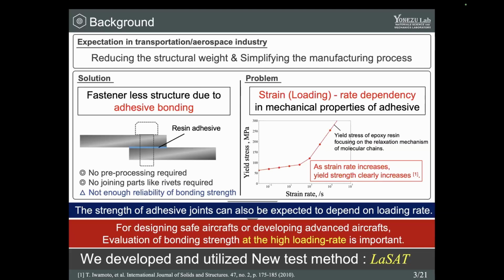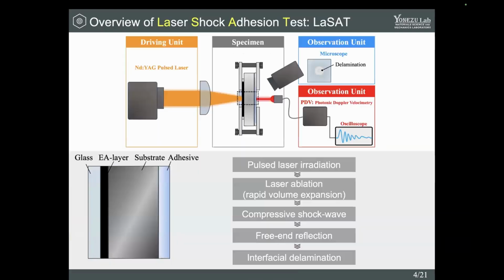One of the reasons for the difficulty in strength reliability is the existence of strain rate dependency in mechanical properties such as yield strength, fracture strength, and deformation stiffness of an adhesive. Therefore, it is expected that the bonding strength of adhesive joints also exhibits a loading rate dependence. So evaluation of bonding strength at a high loading rate is important. As a method at very high loading rate, we have developed and utilized a new experimental method, LASAT. In the next slide, I'll introduce LASAT.